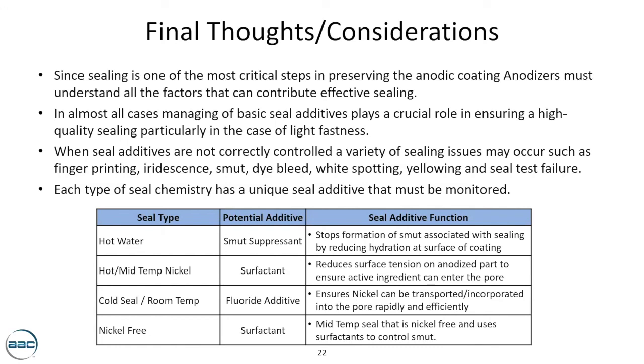If the seal additives are not correctly controlled, you can see issues. For example, with a high fluoride content in the cold seal, you would see some iridescence, and as well, if the fluoride content is low, the part may fail the blue dye stain test or the acid dissolution test. Also, when these additives are not controlled properly, other issues such as fingerprinting, dye bleed, white spotting, yellowing, and seal test failure can occur. It is very important that each type of seal chemistry has a unique seal additive that must be monitored.